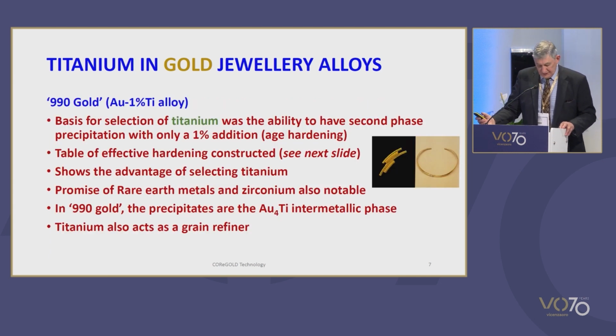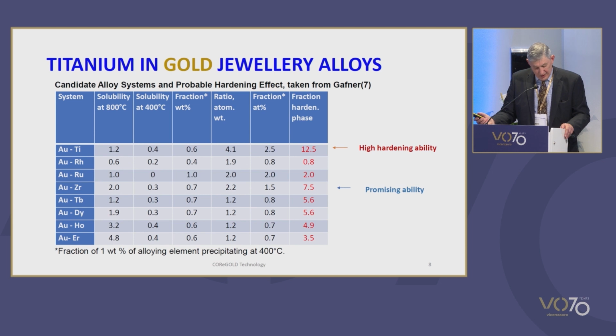The basis for selection of titanium for this alloy was the possibility of second phase precipitation, as an alloy containing 1% alloying addition in solution was cooled from 800 to 400 degrees Celsius, i.e. its age hardenability. From this, a table of probable hardening effectiveness was constructed, which we can see in the next table. The last column makes clear the reason for developing the 990 gold titanium alloy. The promise of the rare earths and zirconium are also noted. In the case of 990 gold, the precipitates are the gold 4 titanium intermetallic phase.